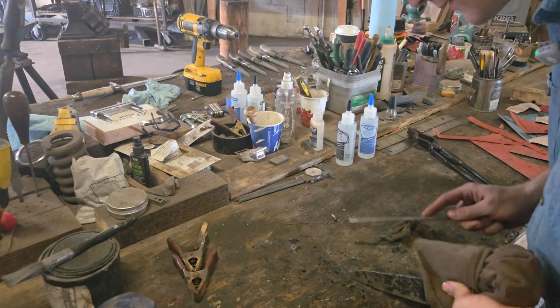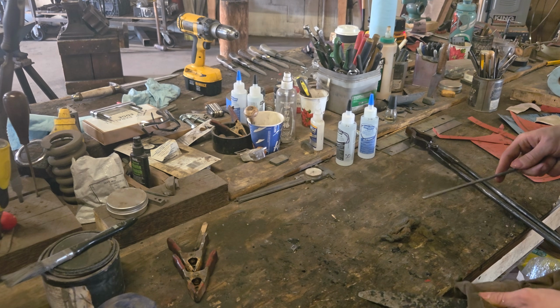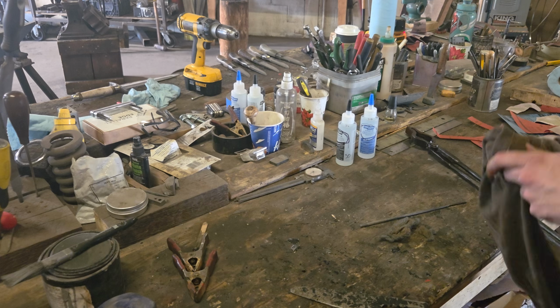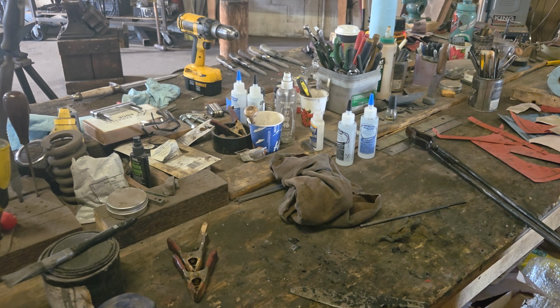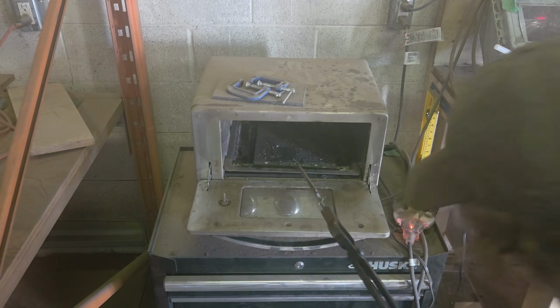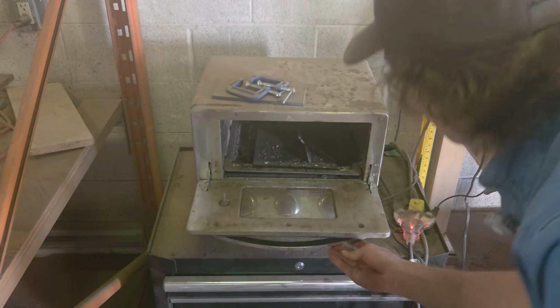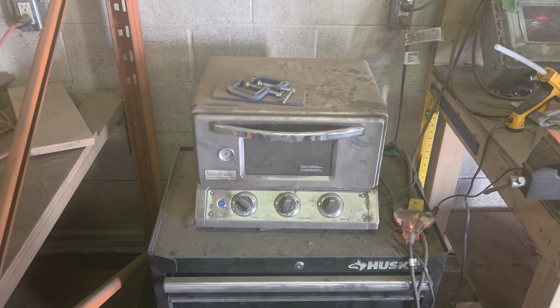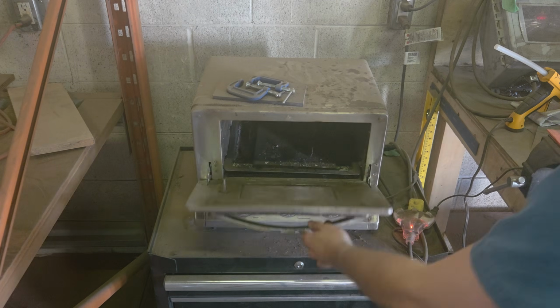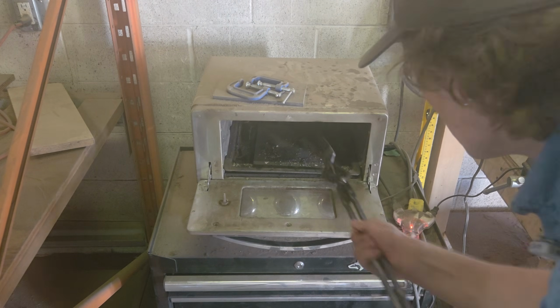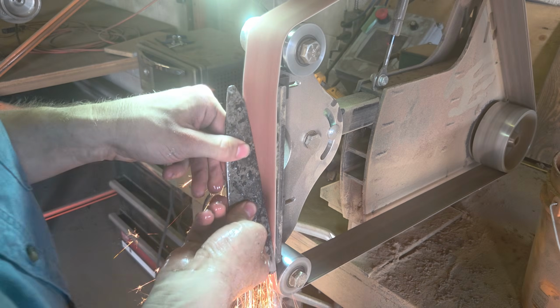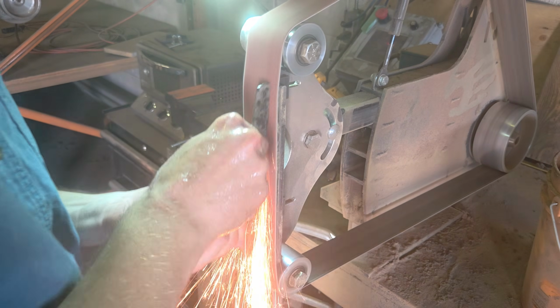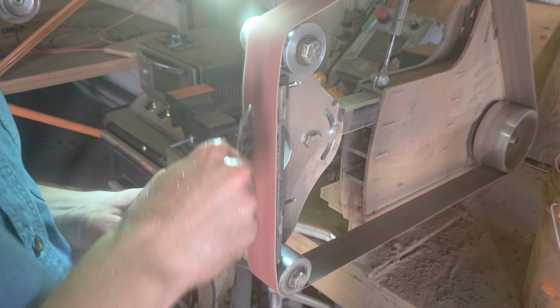Yeah, over the whole blade. Now I gotta throw it into the temper, and then it'll be on to the grinding. For this one, I did 2 30-minute tempering cycles at 325 degrees Fahrenheit. Now, that's a lot shorter of a time than usually recommended for tempering cycles, but tempering is